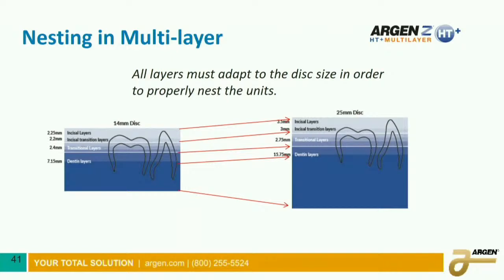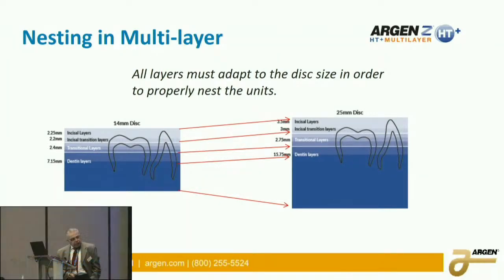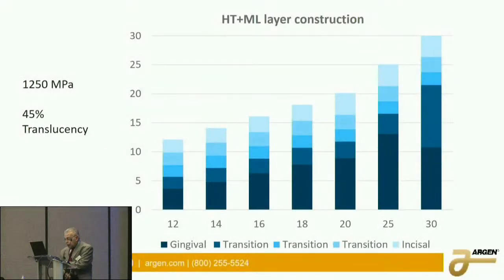So our approach to multi-layer was a little different than the other two. What we do is we keep an incisal layer that's going to work for the case, independent of the thickness of the disc, but we increase it as the disc increases. Somewhat similar to what Katana did, only we have larger transitional layers as well, and a larger dentin layer. So it's sort of like a combination of both of what Katana did and what Ivoclar did. And we find this situation to work very well, especially for large bridges.